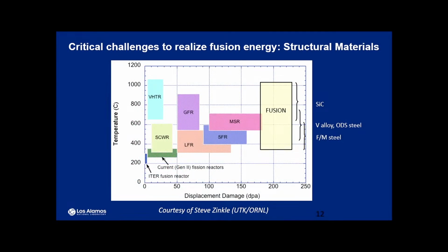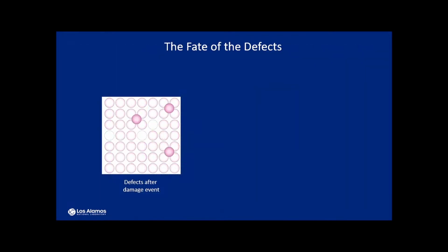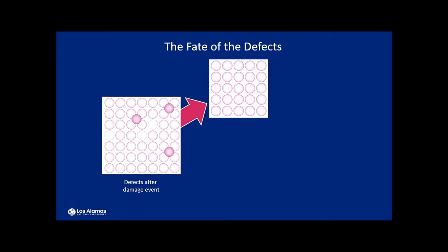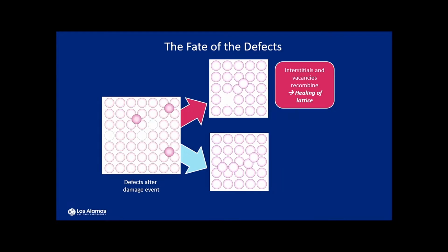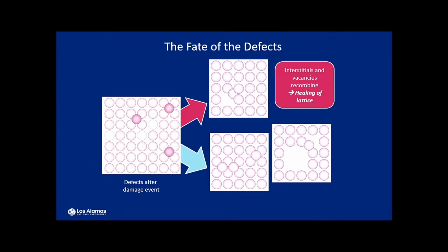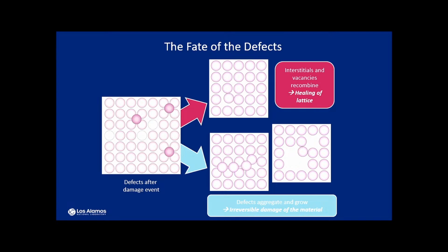Anyway, this is just to show quickly temperature versus the displacement damage. This has been mentioned this morning: how often a lattice atom has been displaced by the energetic interactions. Those defects, when they produce Frenkel pairs, most of them actually recover and cause no damage. We call that the healing of the lattice. But some of those do not recover. They actually form much more complex, irreversible defects in the system. Those are the ones that cause the materials degradation.